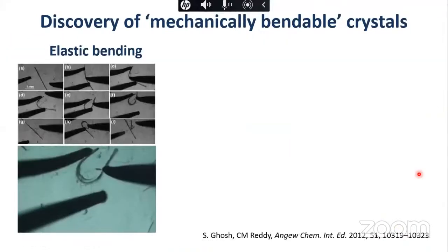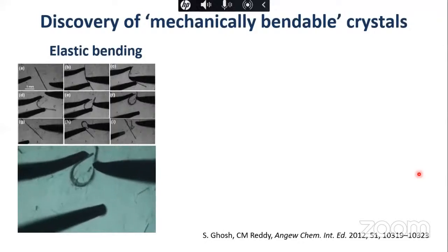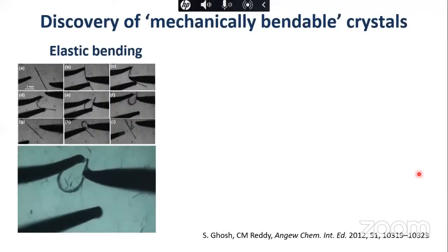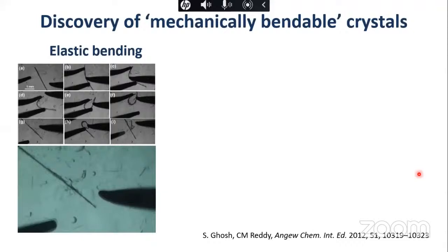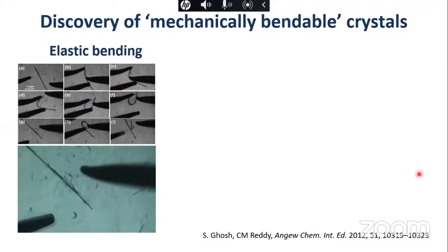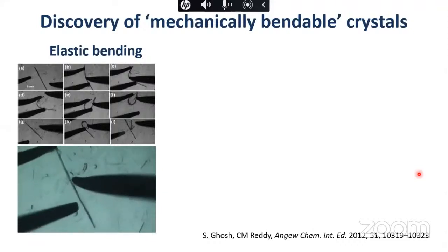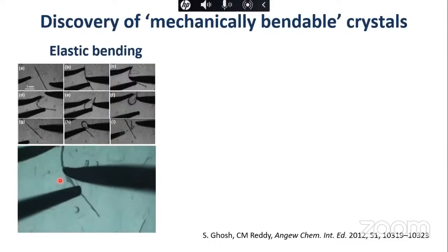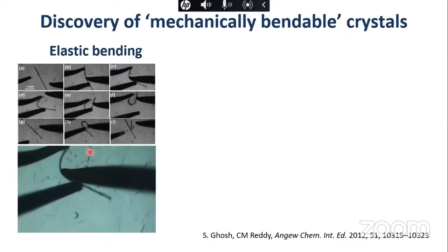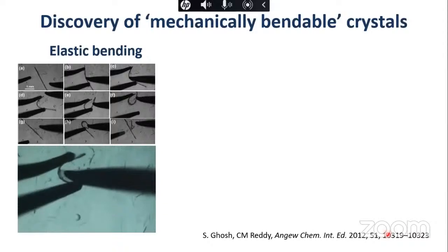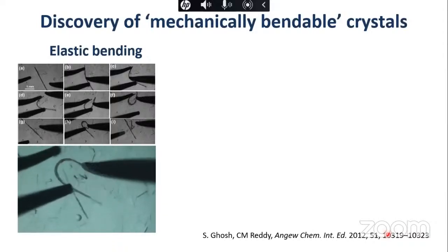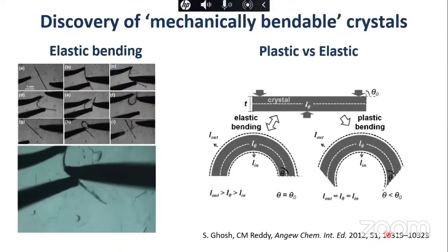So then later we came across elastically bendable crystals. In the previous case, once you bend and leave, the crystals don't come back. But then later we found that crystals can also be elastic. For example, if you can see here, when you bend this crystal and then release the stress, it again comes back very nicely, and so it springs back. So these are called elastic crystals.